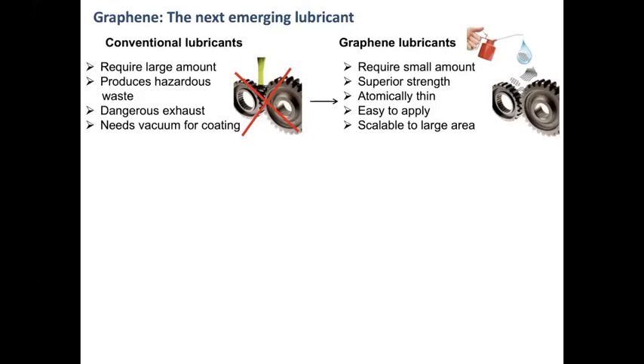With this one, the first material that was considered for all these kinds of applications came from the exploration of graphene. If you think about some conventional lubricants, they require large amounts and produce hazardous waste and dangerous exhaust, or if you use some coatings, they probably need vacuum or specific environment conditions. With graphene, we found that we can get benefits in every one of these different steps and improve the behavior of the system, but also eliminate the need for large amounts, having only these atomically thin structures, protective coatings on the sliding surfaces, and again a very easy way of applying and reapplying these systems.